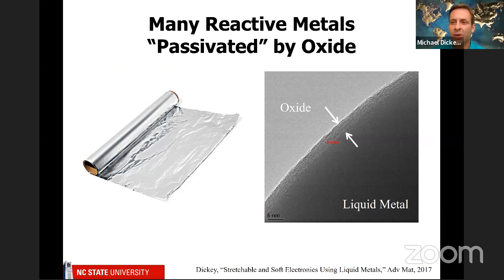So if I've somehow lost you, please come back, because this is really a key point. And that is that this liquid metal oxidizes. And I showed that in the previous video, when you remove it, the metal just beads up. Now, the fact that it oxidizes is really not that surprising. Many metals will react with air and form an oxide, and some of them form a passivating oxide. Passivating means it forms and it doesn't get thicker.